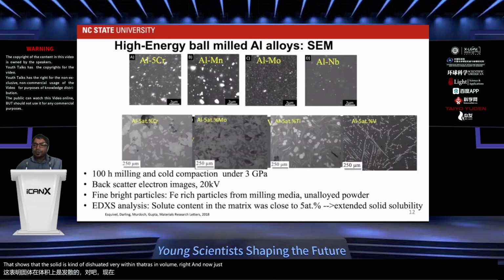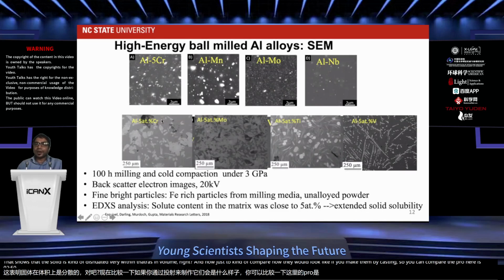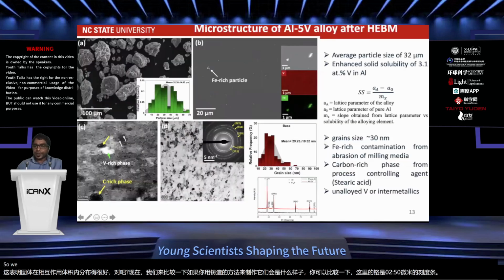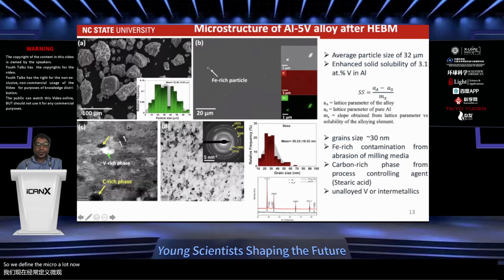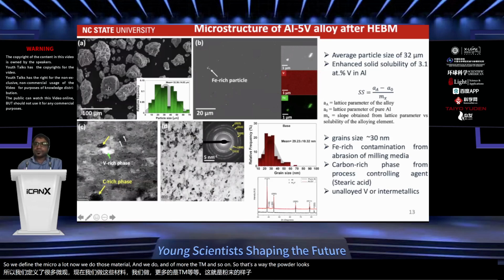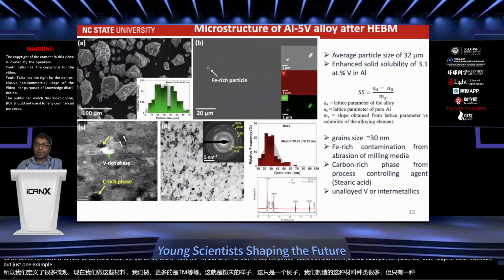Now just to compare how they would look if you make them by casting, you can compare the Al-5Cr here, which is a 250 micron scale bar, right? So we refined the microstructure a lot. Now we took those materials and did more TEM and so on. That's the way the powder looks. And this is just one example. We made a wide range of these materials, but this is just one example of how they could look.